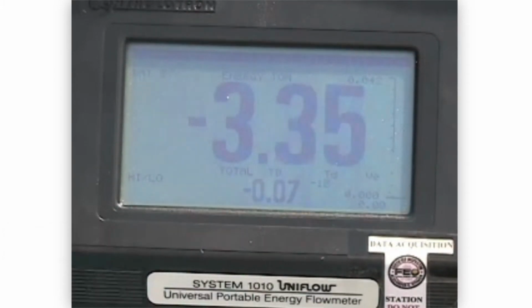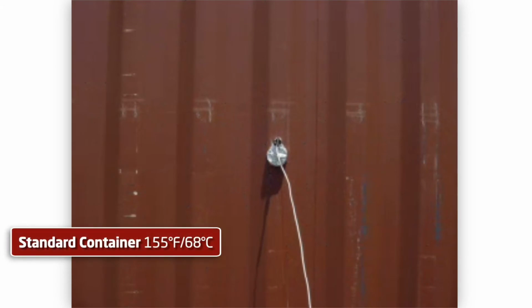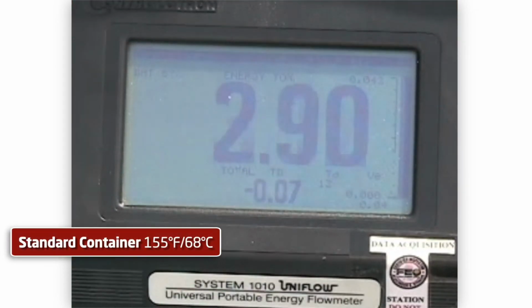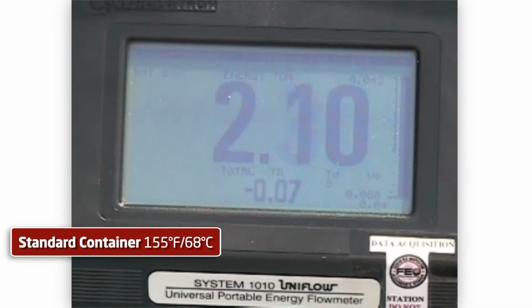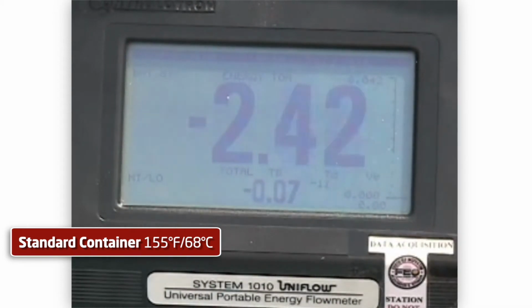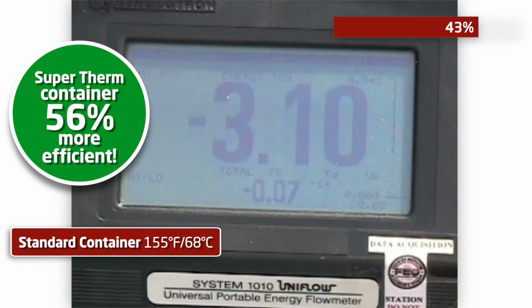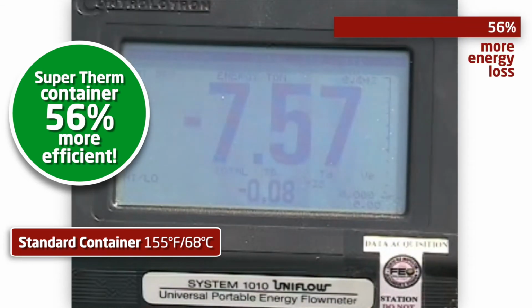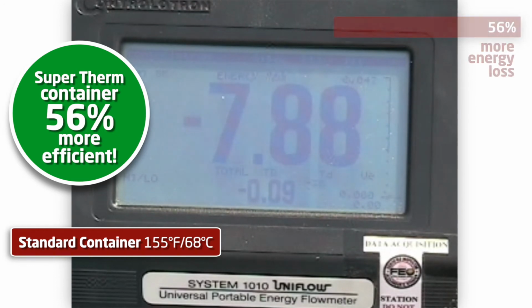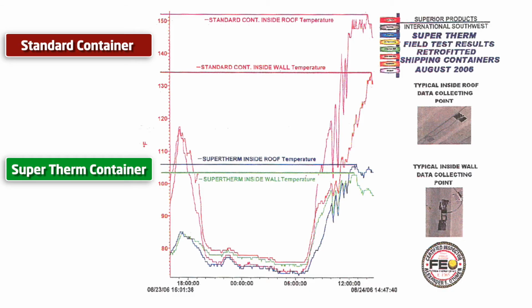An identical test was conducted on the standard shipping container at the same time of day under the same weather conditions. From this specific point, you can see that the standard container's losses are exceeding the losses of the container retrofitted with the Super Therm product. The end result was almost a 50% increase in thermal transfer.